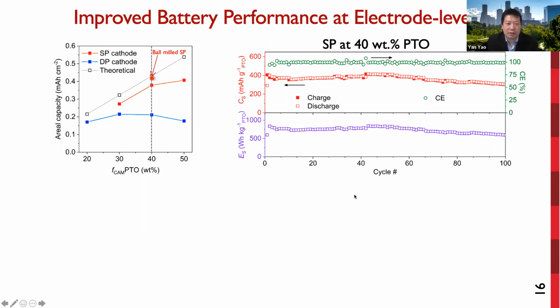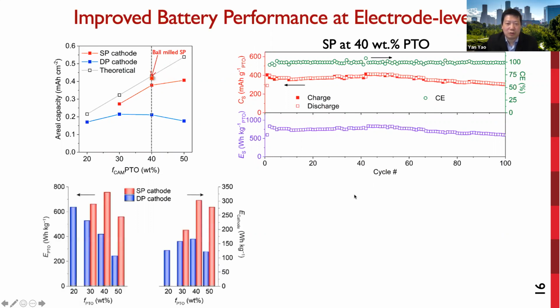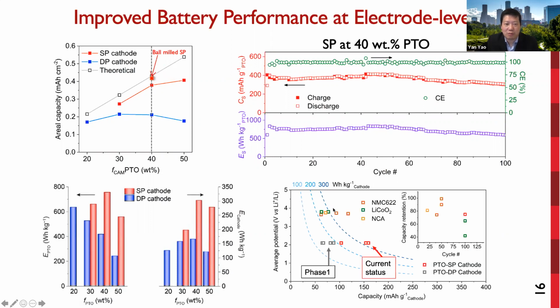We also compare the specific energy considering the total cathode mass in this figure. The value can reach 300 watt-hour per kg, which is on par with inorganic cathodes such as lithium cobalt oxide, which has a lower capacity but a higher voltage. But we show better cycling is possible without any coating applied.